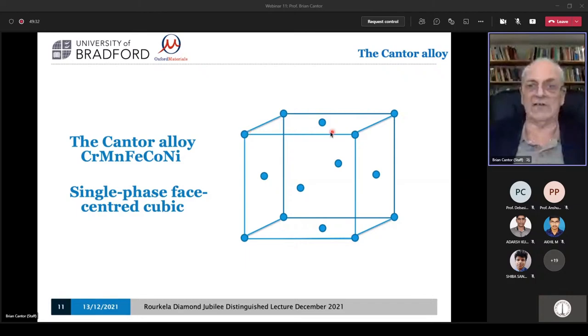So this is the crystal structure. Here are atoms in a face-centered cubic array, an atom at the corner of each cube and at the face center. And you can imagine stacking these up. Well, most metals have this face-centered cubic structure. It's why they're so soft and formable and why they're so fracture resistant, unlike most other materials. I'll say why in a second, but copper, gold, aluminium, lead, silver, lots of metals all have this face-centered cubic structure. It's why they're so soft and can be beaten out and formed into shapes. The reason is that in this structure, the atoms can roll over each other by a very special mechanism, which I'll mention later.